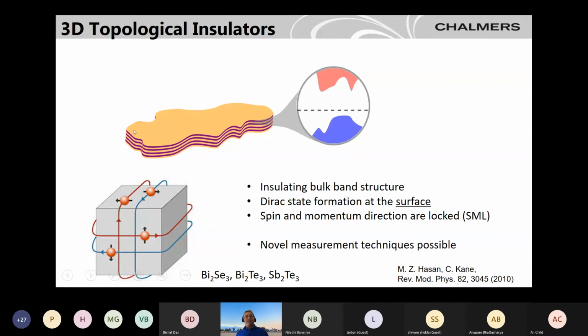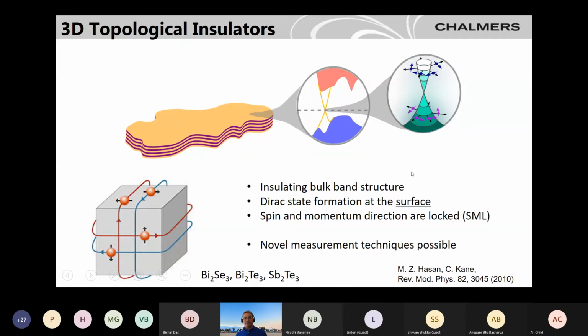Okay, then coming to 3D topological insulators, maybe most of you know that in the bulk materials, bismuth selenide and tellurides, you can find that the surface is conducting with spin polarized electrons, and the bulk is an insulator. So the bulk is the insulator, but if you go to the surface, it has these edge states, and these can be spin polarized, for example, spin momentum locking. So momentum and spin are 90° to each other. And this can be quite interesting for spintronic measurements.